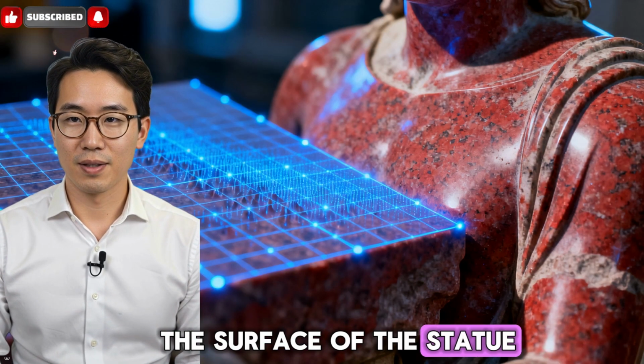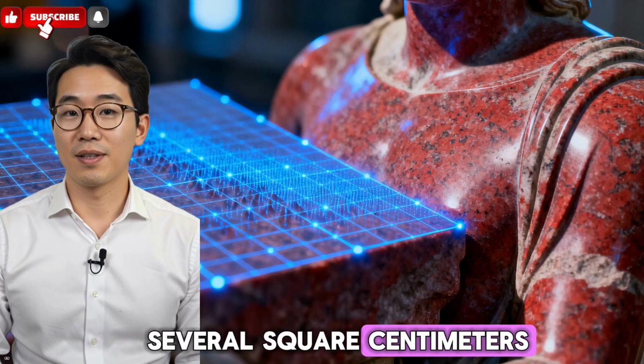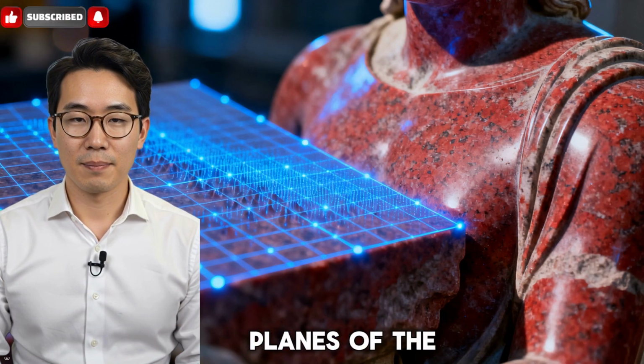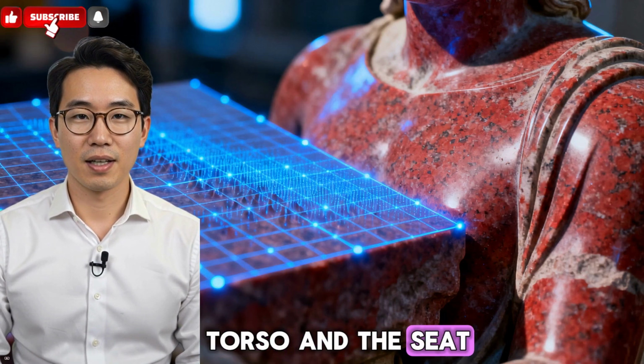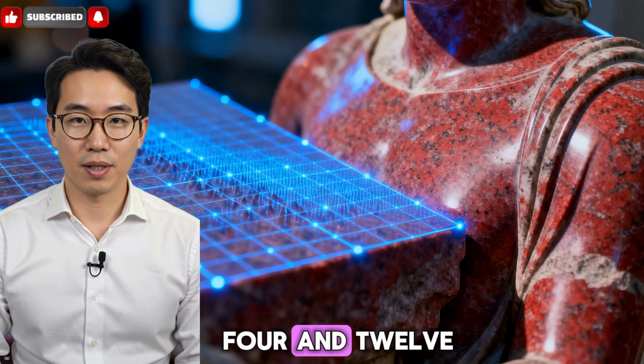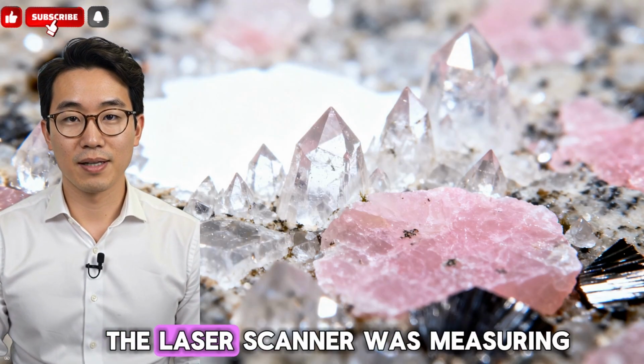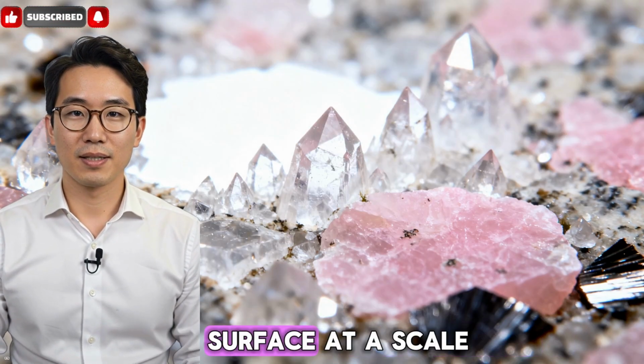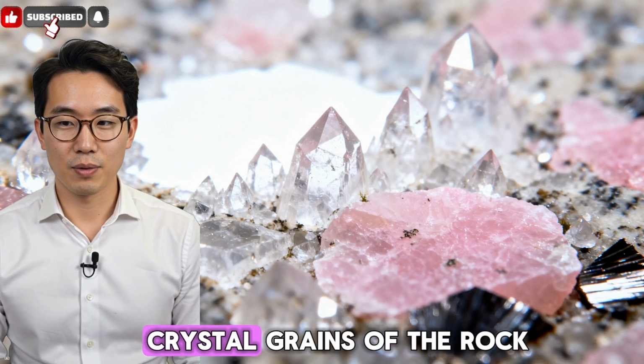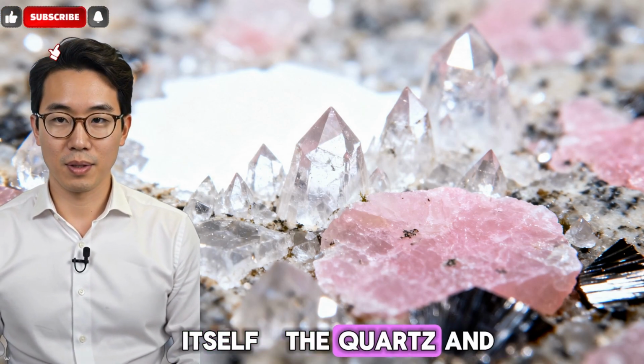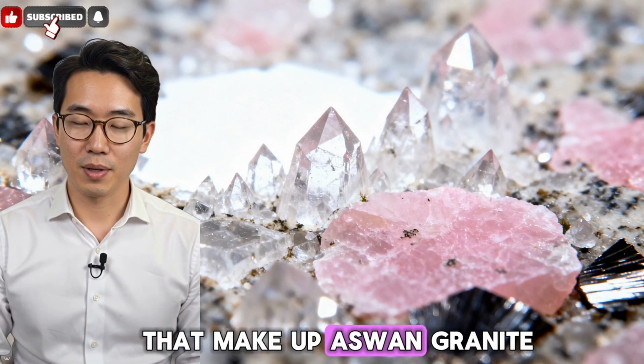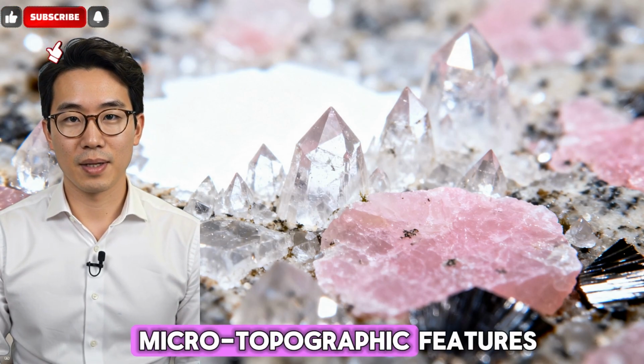The surface of the statue, across areas of several square centimeters measured in multiple locations on the flat planes of the torso and the seat, showed flatness variations of between 4 and 12 thousandths of a millimeter. The laser scanner was measuring the topology of the granite surface at a scale where the individual crystal grains of the rock itself, the quartz and feldspar and mica that make up Aswan granite, are visible as microtopographic features.